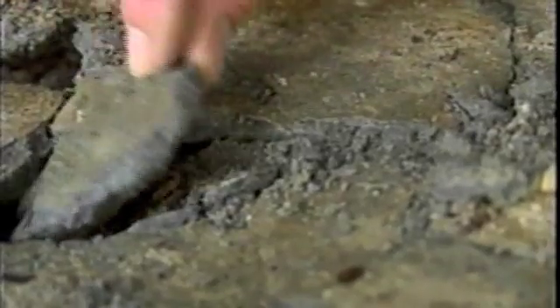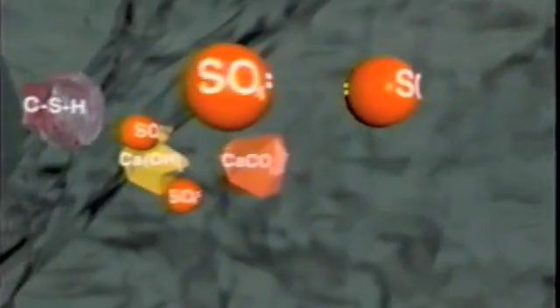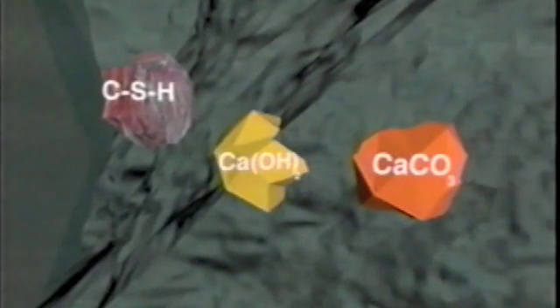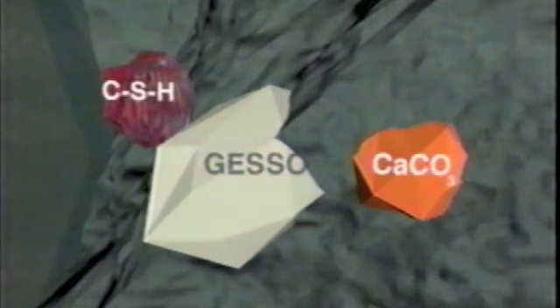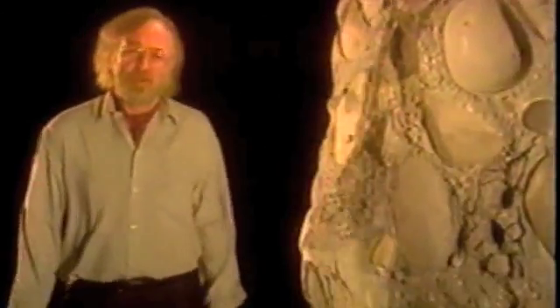In certain very special environmental conditions, the effect of the sulfate on the concrete can be even more dramatic. At a temperature of between 0 and 5 degrees Celsius, with relative humidity of over 95%, and in the presence of carbon dioxide, the sulfate combines with calcium hydroxide and transforms it into gypsum. The gypsum, in its turn, reacts with the calcium silicate hydrates, here indicated as CSH, and the calcium carbonate CaCO3, producing thaumasite. Thaumasite breaks down concrete, changing its internal characteristics completely.